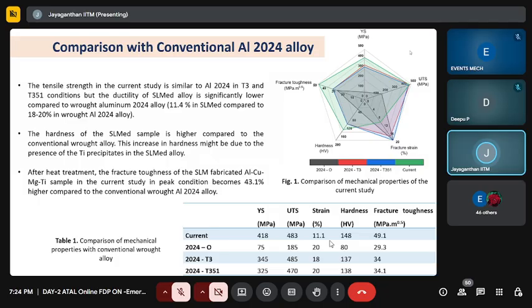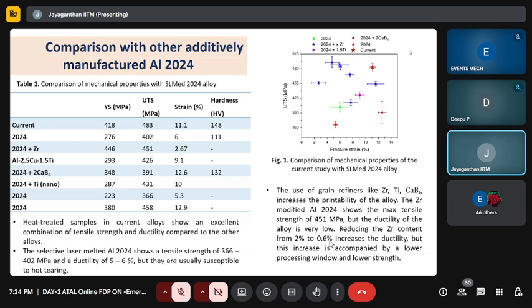And we are comparing, in fact, just to highlight this whole discussion, what you see from this table: 2024 alloy, the current alloy, and the alloy produced by the other route, 2024 O, T3, T351. All these O, T3, T351 refer to different heat treatments. We have compared the material produced by 3D printing, the current work, titanium added aluminum 2024 alloy. You look at their yield strength, ultimate tensile strength, typical strain, how much it can take, hardness and fracture toughness. We have compared our 3D printed alloy with a conventionally prepared alloy. You can see from this table.